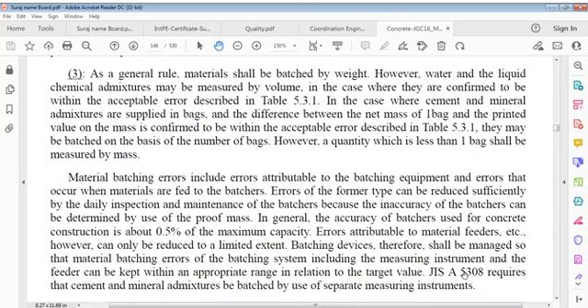However, water and liquid chemical admixtures may be measured by volume in case where they are confirmed to be within acceptable error. In case where cement and mineral admixtures are supplied in bags and difference between net mass of one bag and printed value of mass is confirmed to be within acceptable error, this may be batched on basis of number of bags. However, a quantity which is less than one bag shall be measured by mass.